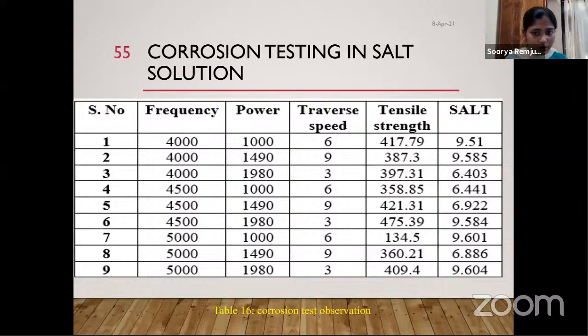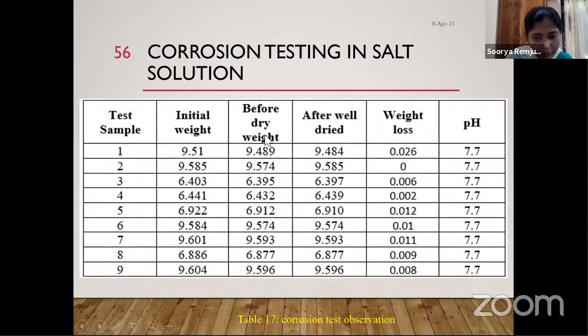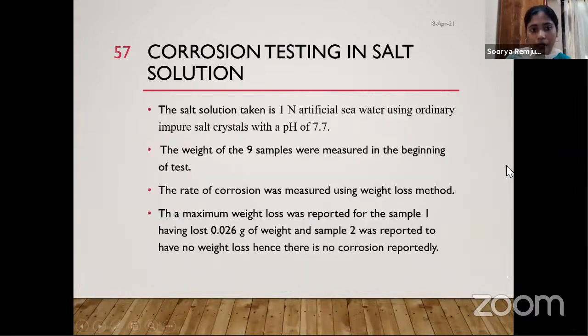Now corrosion testing in salt solution. The initial weights in salt for these 9 samples are recorded here, and the final weights are given here. Initial weight 9.51 means final weight 9.48, so the weight lost was 0.026. For the pH of 7.7, that is in salt, among all the samples, the maximum weight was lost by sample number 1, whereas the least weight was lost by sample number 2. So that states there is more corrosion for sample 1, and no corrosion for sample number 2.